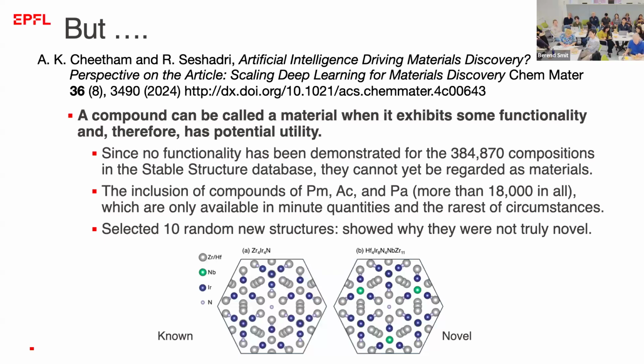You can easily do that on a computer. You can put them on those crystallographic positions, but getting there experimentally, since the metals are so similar, it will most likely be a random distribution. The other thing they were observing is that these were based on DFT calculations, and if you increase the temperature higher than 0 Kelvin, you can have symmetry transitions, and that's not a new material. So of the 10 randomly selected materials, they were basically saying they were not really truly new.